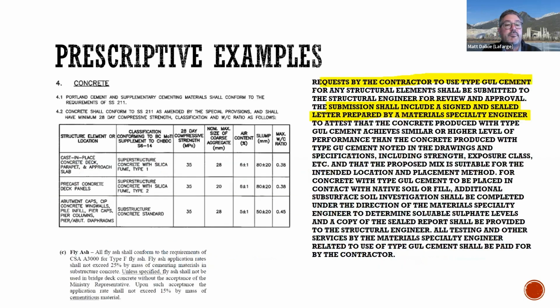Some examples of prescriptive specifications. Here's one on the left. You can see here it's not uncommon to see strength. In this case, they have a maximum coarse aggregate size. They have air content listed here. They have slump and a maximum water to cementitious materials ratio.